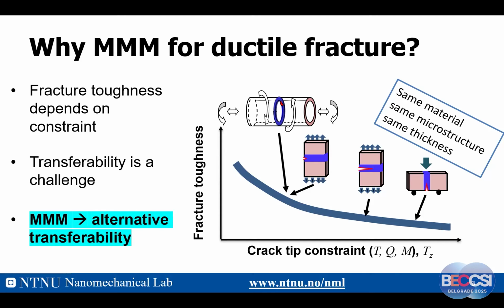So here we have what I have plotted, that crack-tip stress fields may be controlled by T-Z. Professor Guan has a fantastic talk today about the T-Z constraint parameter. But in general, what we are telling is that the fracture toughness is not a constant. It depends on the crack-tip constraint. Transferability is a challenge. We cannot transfer from one geometry to another one. That's a challenge. And what we can demonstrate is that micromechanical modeling could offer alternative transferability. That's my starting point. I will end my talk on transferability.